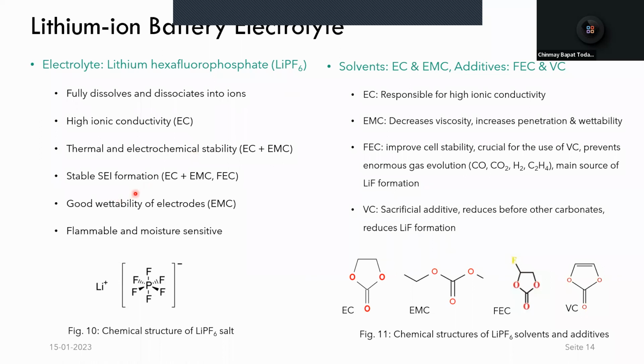SEI is basically a solid electrolyte interface layer that is formed at the anode. It is formed when the electrolyte decomposes and deposits on the graphite anode in the form of a passive layer. Now, this layer has to be passive. Otherwise, more and more electrolyte will get decomposed and deposited onto the anode, and we'll have a loss of usable lithium ions. So this lithium hexafluorophosphate dissolved in these particular solvents offers stable SEI formation and cycling stability. It also offers good wettability of electrodes. That is, the electrolyte can penetrate through the electrode better.